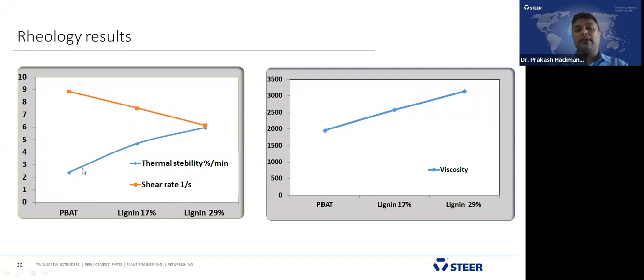When you talk about the rheology study, with the addition of lignin the thermal stability increases. If you see the graph, PBAT is the base material showing this stability. With the addition of 17% and 29% lignin, there is a slight increase in thermal stability. As I already explained, lignin helps with lubrication, and the addition of lignin reduces the shear rate. As for viscosity, the addition of lignin increases the viscosity of the final compound slightly, going up from the PBAT value to this.